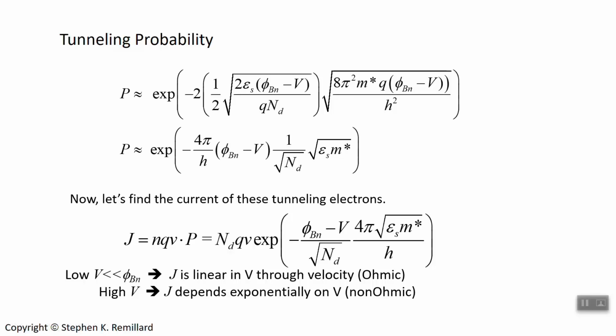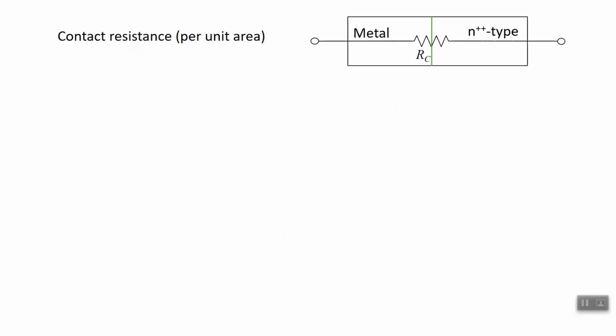This metal heavily doped semiconductor junction is like a normal conductor at low voltage. It is ohmic. At high voltages, it's non-ohmic. It operates as an ohmic contact at low voltage. Let's look at the contact resistance. And this is possibly your first connection with using this quantity. Here's the metal, here's the semiconductor, and there's the junction. There is a resistance associated with that contact.